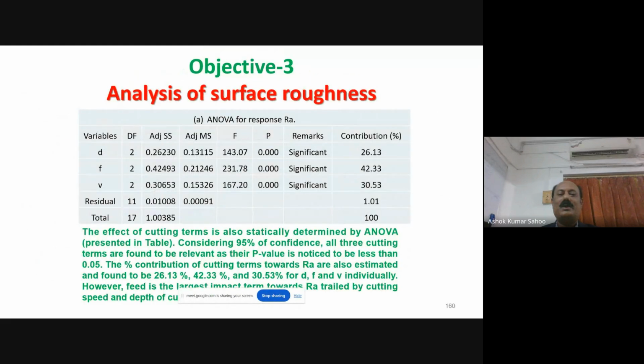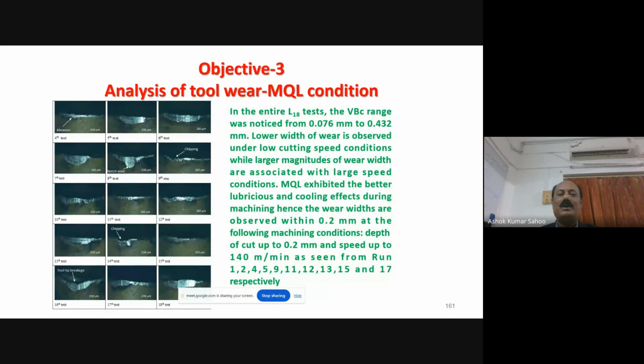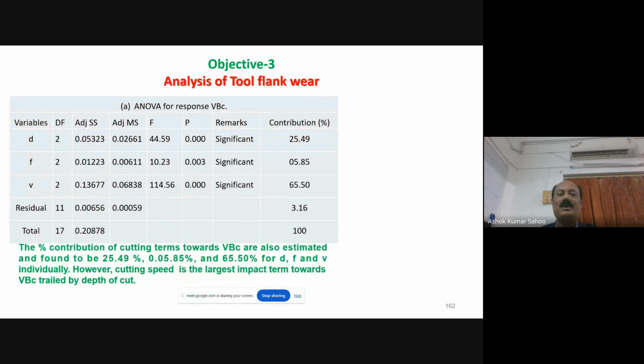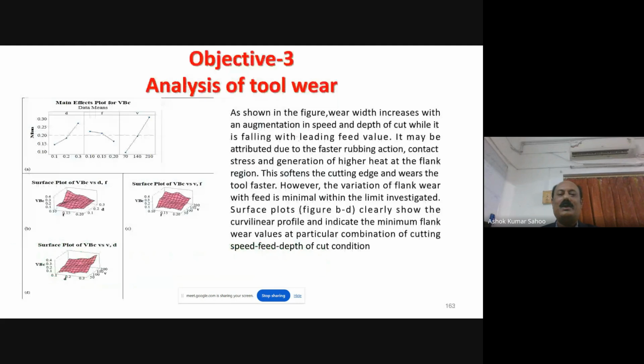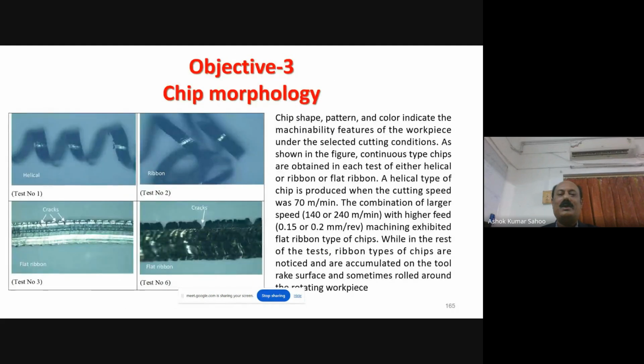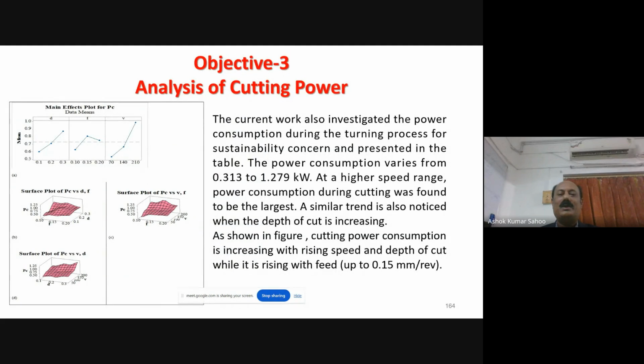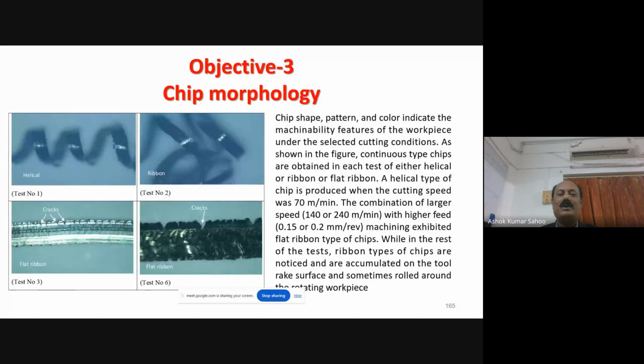and for surface roughness, depth of cut, cutting speed, and feed are significant as per ANOVA, and feed is found to be the most significant parameter. For flank wear, cutting speed is found to be the most significant parameter, and for cutting power also, cutting speed is found to be the most significant parameter.